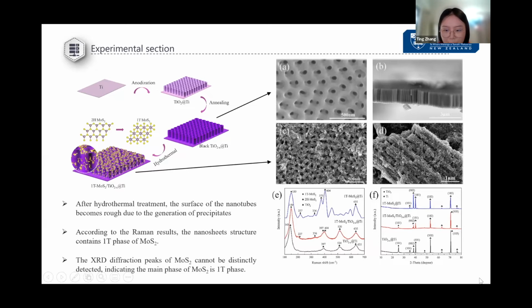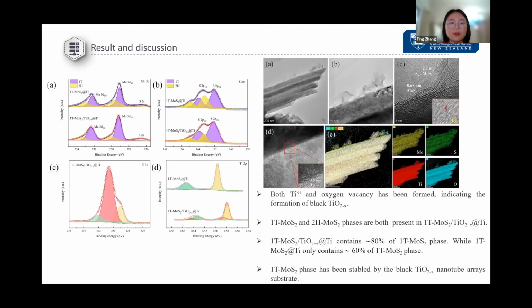According to the Raman and XRD analysis, we can say that the MoS2 nanosheet contains both 1T and 2H phase. The reason that we combine the black titanium dioxide and MoS2 nanosheet is to enhance the content of 1T phase and stop the 1T phase from transferring to the 2H. So it's really important to calculate whether the content of the 1T phase has been enhanced or not. So we did the XPS analysis.